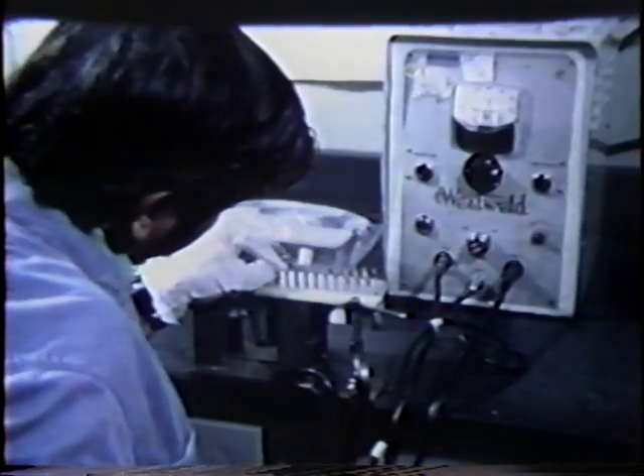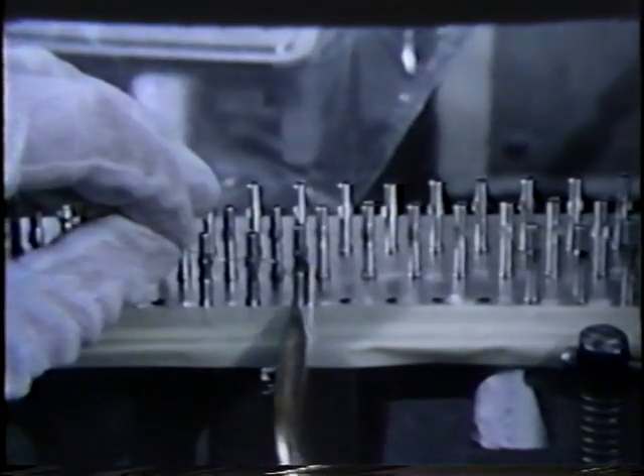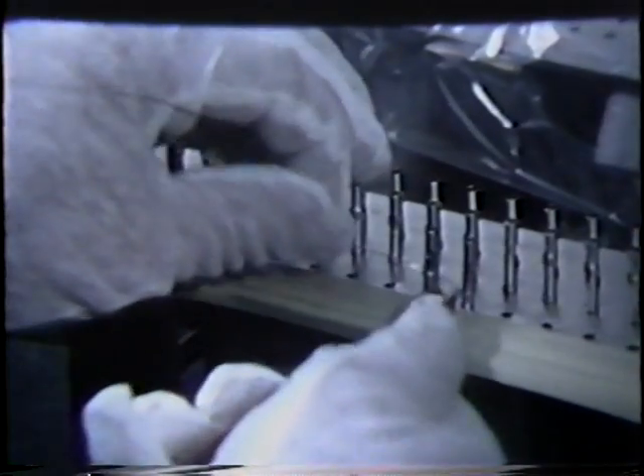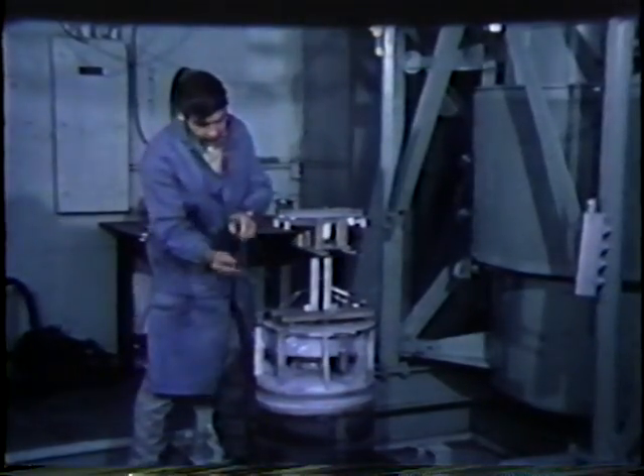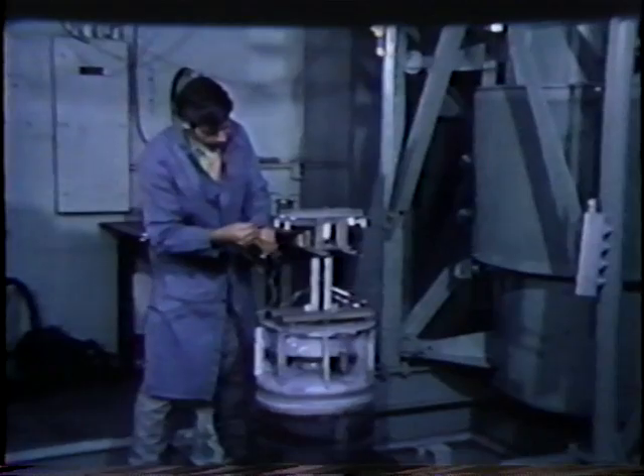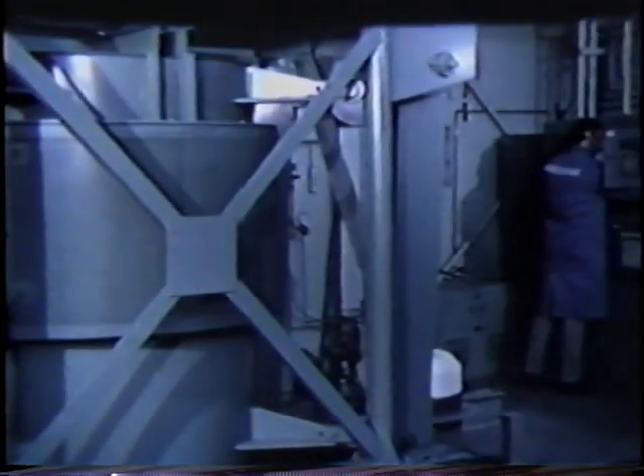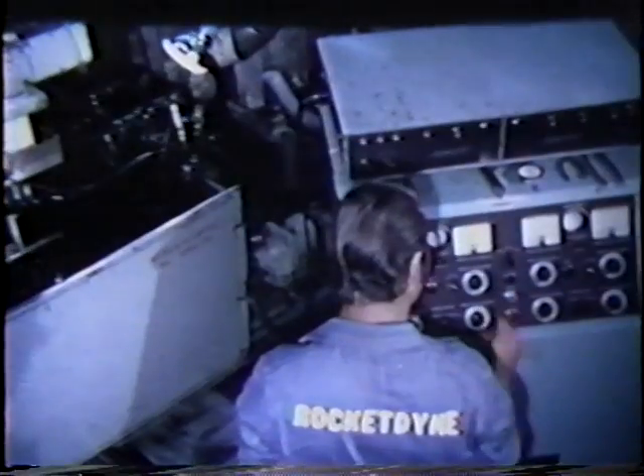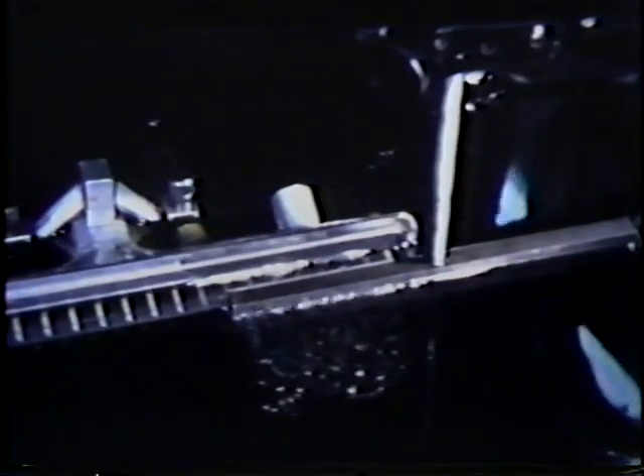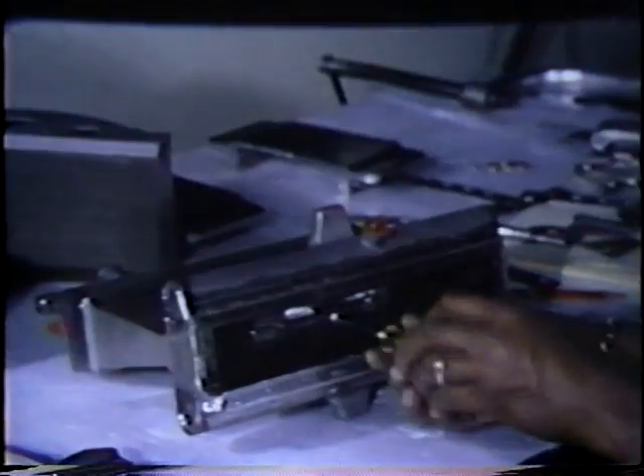The injector uses a concentric element design. The elements are coaxial, with liquid oxygen in the center post and gaseous hydrogen in the annulus. The single up-pass cooling circuit selected for the chamber allows use of a simple hydrogen flow circuit in the injector. The injector braze assembly consists of the stainless steel injector dome with 68 injector posts, each of which includes an oxidizer orifice. The 68 injector posts are brazed to the body in one vacuum furnace cycle. The posts are trimmed by electrical discharge machining, ensuring clean, even ends without danger of damage or contamination.